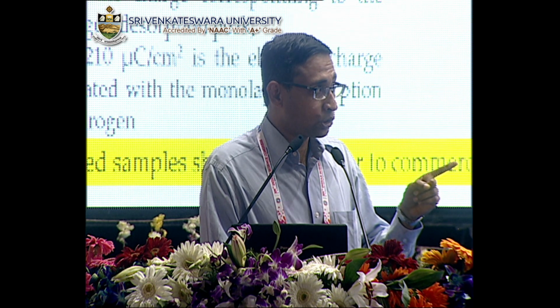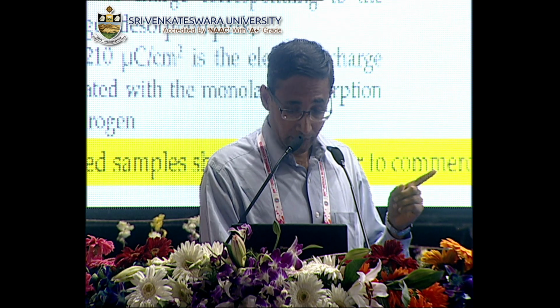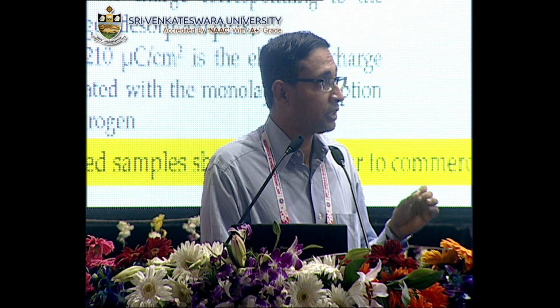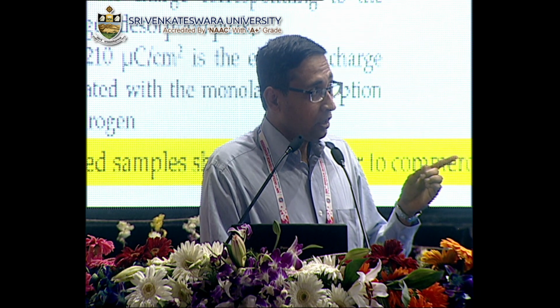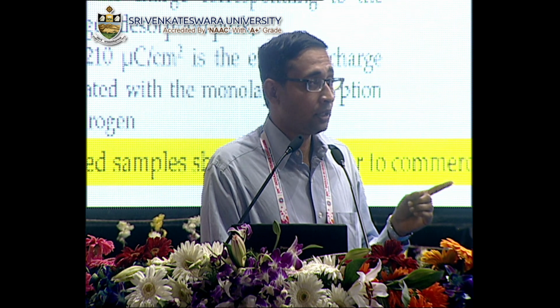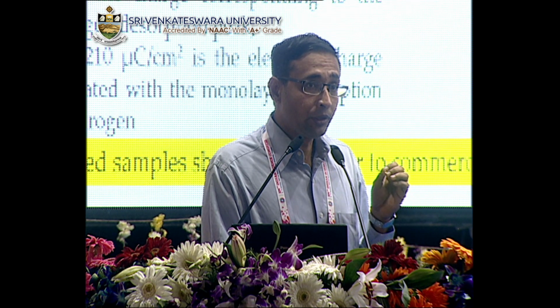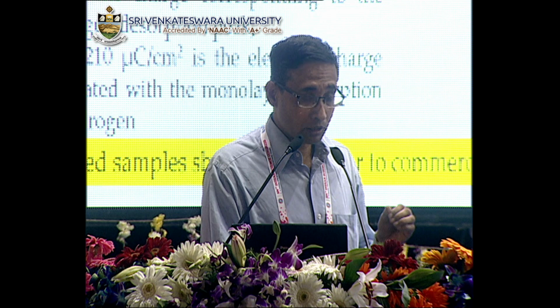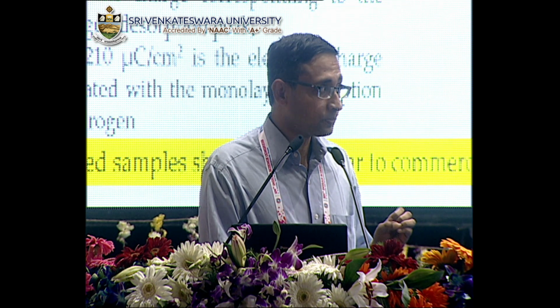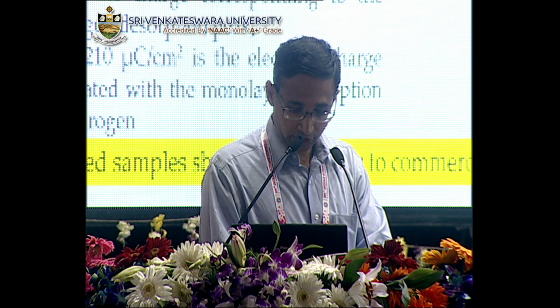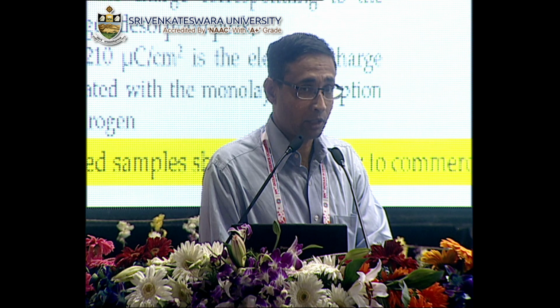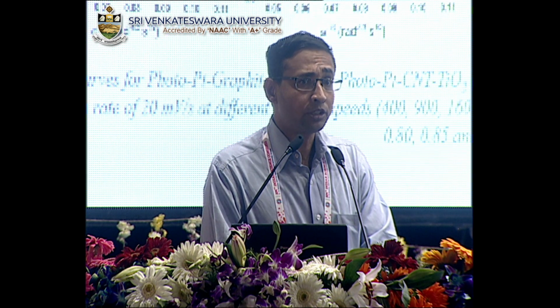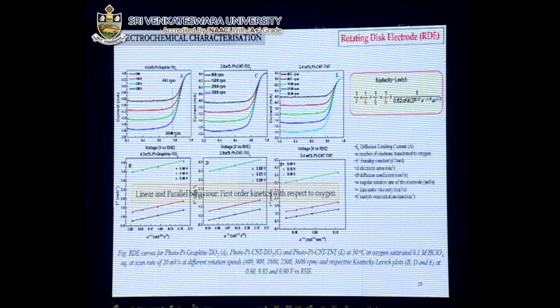The commercial catalyst is the bar at the right hand most corner, and this is around 77 ECSA, electrochemical surface area, in square meters per gram. We see that our catalysts, the CNT based ones, are almost on par with the commercial catalyst. Here I would like you to note that the catalyst which we have prepared has at a maximum 58% of platinum, which is 10 times lower than the commercial catalyst, and still it behaves close to the commercial catalyst. Now there are other techniques which further substantiate that our electrocatalyst is usable, some electrochemical characterization which also depicts the mechanism in which the electrocatalyst can function.